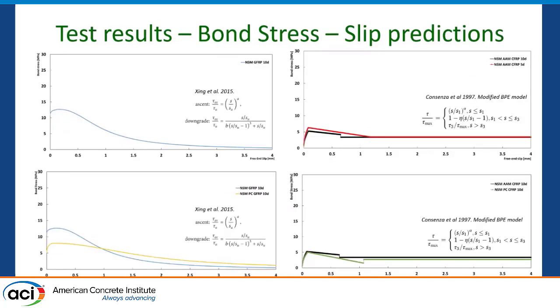So here again the bond stress slip prediction behavior was the best with the model by Xing in 2015, and for carbon fibers with alkali-activated materials and with Portland cement, we had the best correlation with the modified BPE models proposed by Cosenza in 1997.